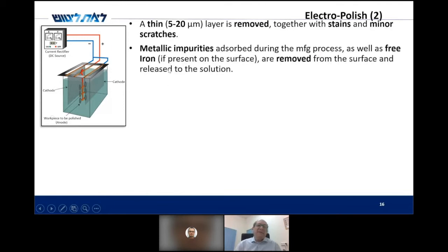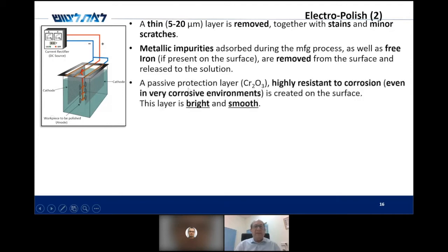The nice thing about it is that the metallic impurities absorbed during manufacturing, like free iron, if present on the surface, are all removed from the surface and released to the solution as part of this electrochemical process. This passive protection layer that is being built on top of the workpiece is highly resistant to corrosion, even in very corrosive environments. And I will show the difference between classical passivation or chemical passivation to electro-polish later on. And of course, because of this removal, the layer is also bright and smooth.